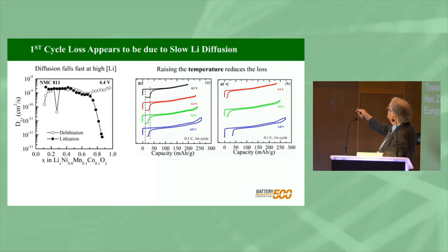But first, let me just show you what happens as we change the charging voltage. Increase the charging voltage, we take more of the lithium out. So this is 4.2 all the way to 4.8. And we put this one in here to show you that we're now getting a separation of the charge and discharge cycles. And this is because at 4.8 volts, the system is unstable and the electrode materials is reacting with the electrolyte forming resistive materials on the surface. There's a little bit of it here.